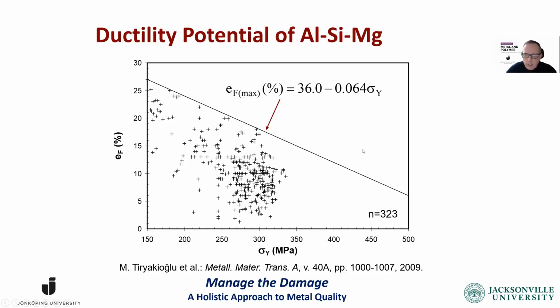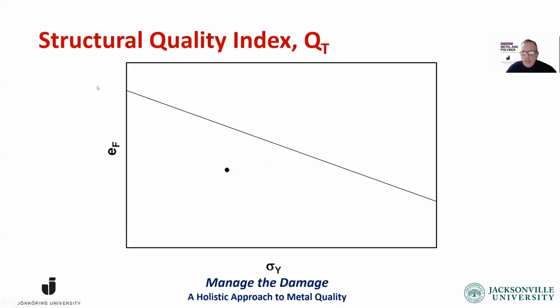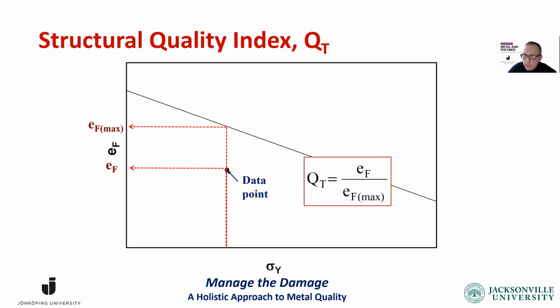So the best fit to this maximum line, or ductility potential line, for aluminum, silicon, magnesium alloys is 36 minus 0.064 times yield stress. Okay, how can we use that? I propose that we have a quality index. When we run a tensile test and have our data points, basically we need the yield stress and the elongation. Then based on the yield stress, we calculate the ductility potential. And basically the quality index is the elongation that we get from the tensile test divided by the ductility potential that would come from that simple equation. So we can get an idea of how much we're getting from the metal.